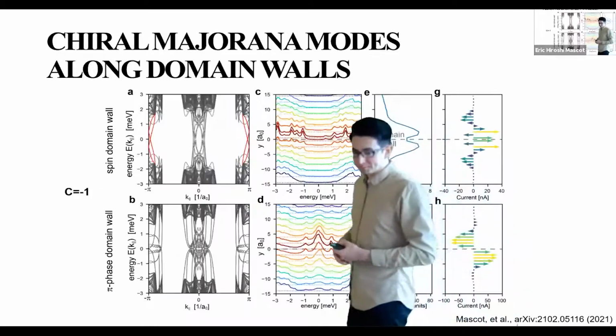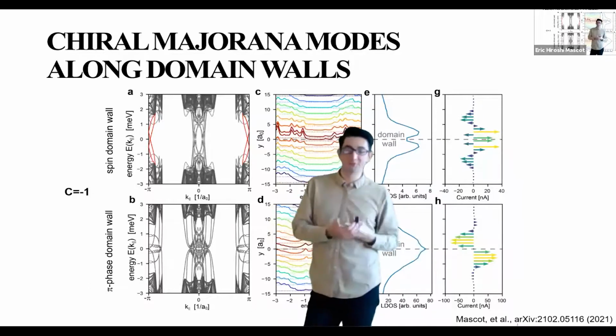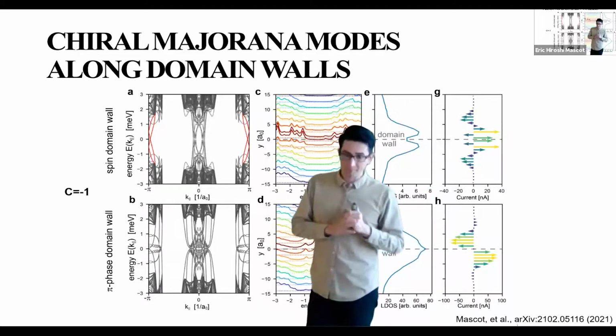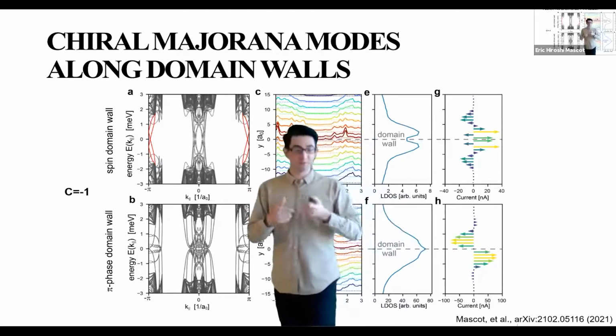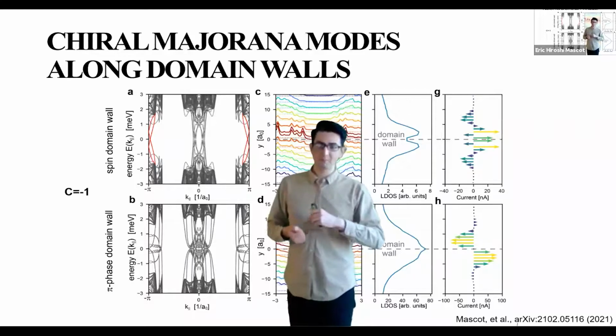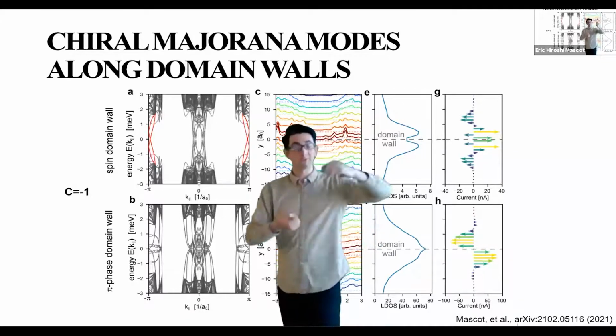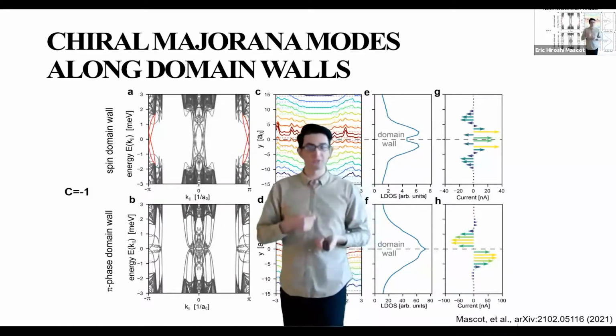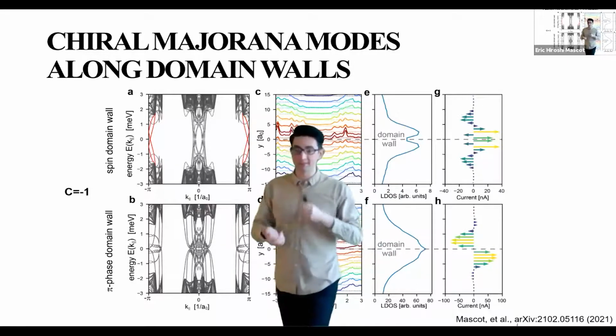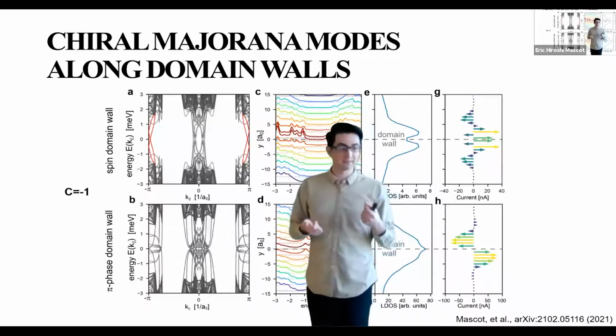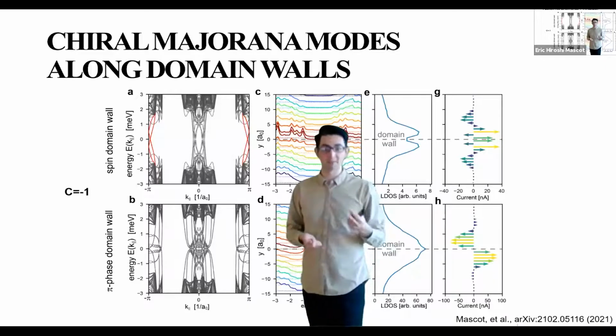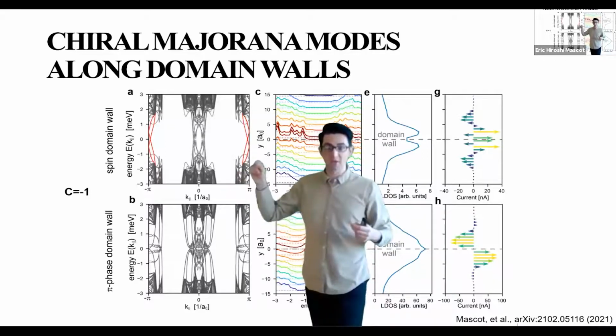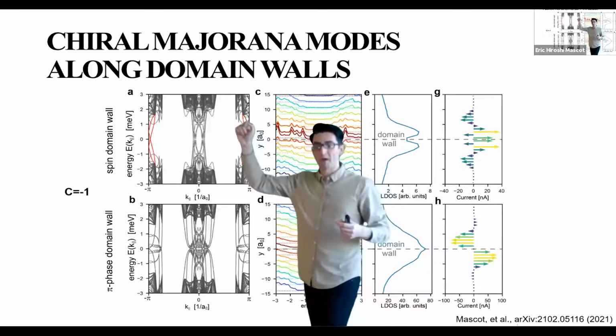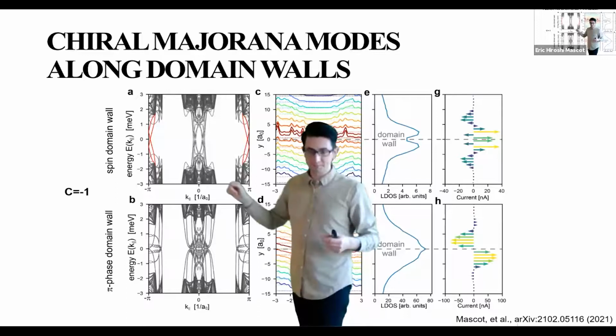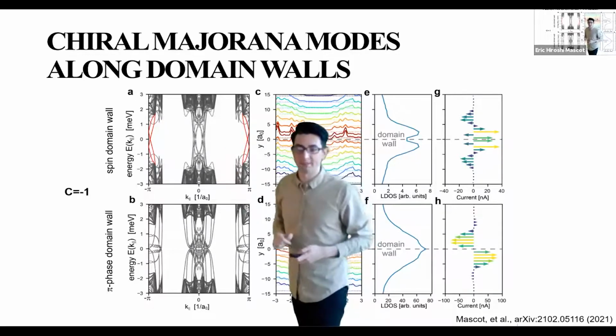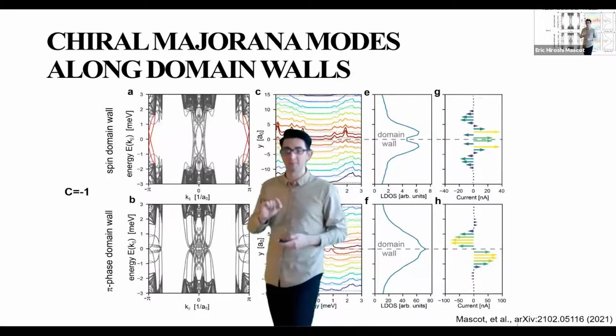And lastly, to compare to the domain wall, we looked at two different types of domain walls. So we look at spin domain walls, where we flip the ferromagnetic ordering on the surface. And in this case, when you flip the spin, then you flip the Chern number. And so the difference in the Chern number is 2. So we expect from the bulk-boundary correspondence two topological edge modes, which we see, these two crossing the superconducting gap. And we also see these trivial edge modes, but these are gapped in the very center, with a very, very small gap, and those are trivial edge modes.